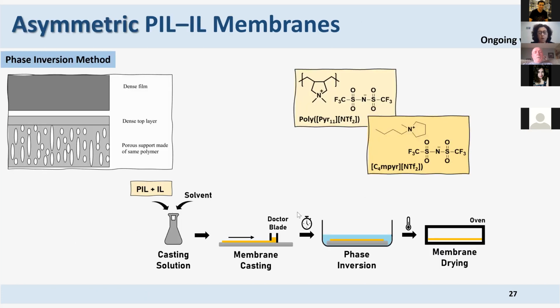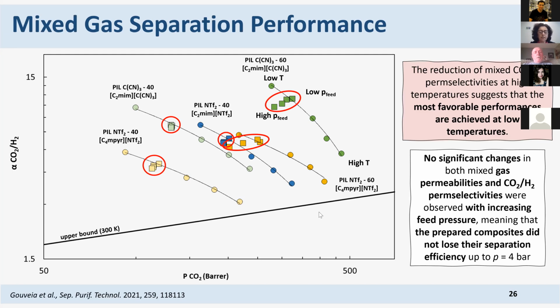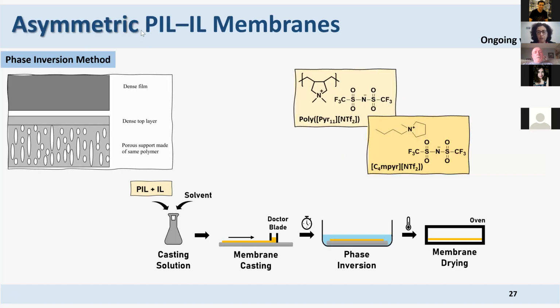Okay, so what we've seen here is that we use a dense membrane, and this really illustrates the problem that these membranes have, which is that the flux, the CO2 permeation, is quite low. And so we tried to prepare asymmetric film membranes, and this is still ongoing work. So Andrea has been working desperately on this in the lab so that she can finish. And so instead of having a dense film, we are trying to create a dense top layer and a porous layer to support the dense layer. So we use exactly the same polymers.